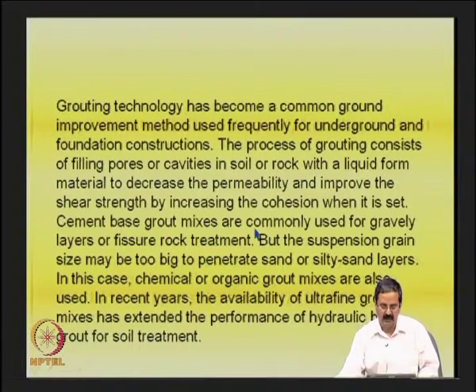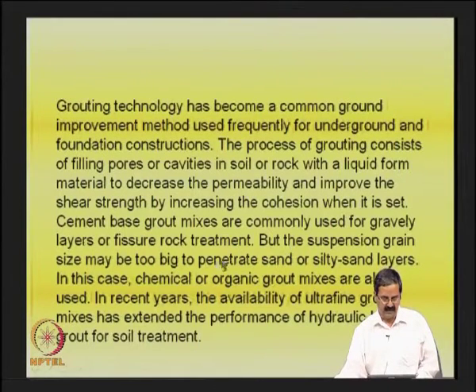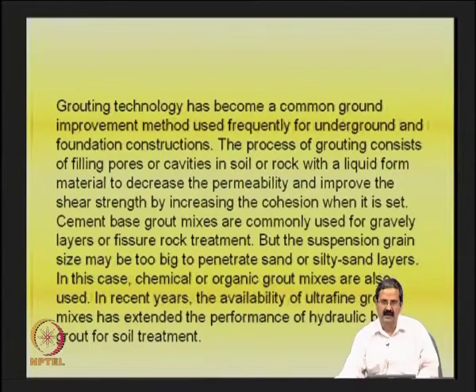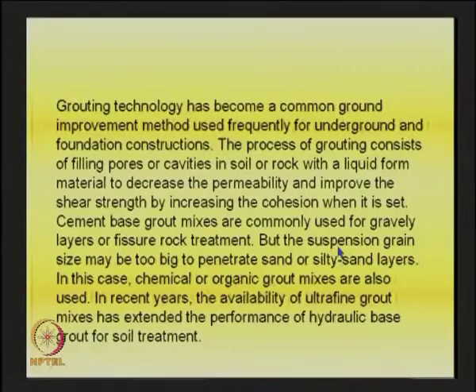Cement-based grout mixes are commonly used for gravelly layers or fissured rock treatment. But the suspension grain size may be too big to penetrate sand or silt layers. The particle size is very important — the grout material should get into the soil system and stabilize the whole area, occupying all the voids. When the grain size distribution of the soil is very fine, the suspension may not penetrate, so we use chemical or organic grout mixes, which are quite useful in those conditions.